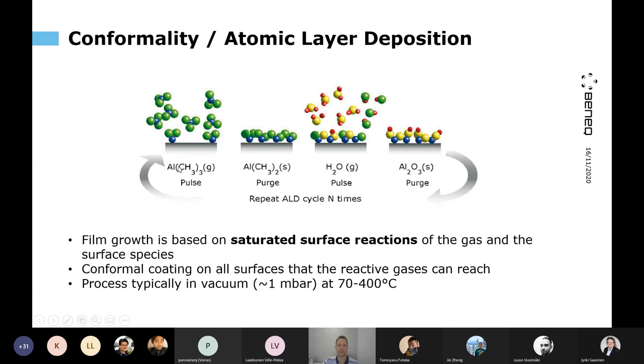In this case, this is what we call TMA, so trimethyl aluminum, but it can be many other things, but that's the example here. So the TMA molecule comes in, and it starts to react with the surface as long as it can find free surface sites. And it will continue reacting on the surface, and eventually all the surface sites will be occupied, and we say that the surface has been saturated. So there is no more deposition happening.